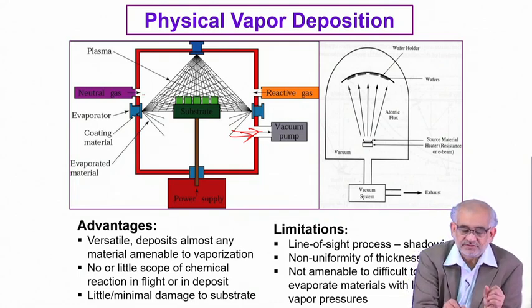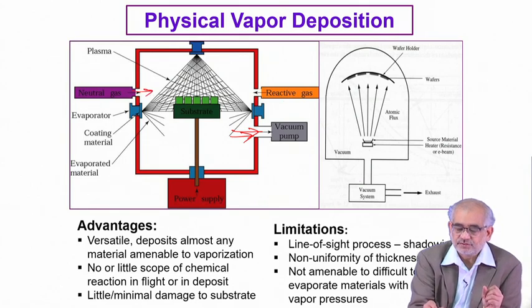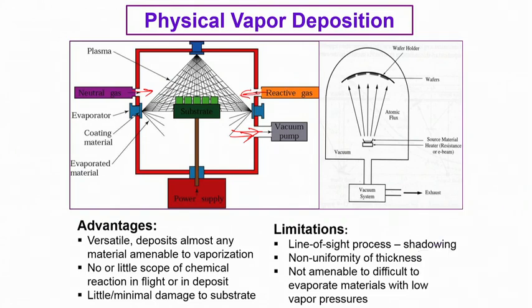You can backfill with neutral gas such as argon, or you can also feed in oxygen or nitrogen if you want certain reactions to take place, though this is not very regular. Feeding argon is fairly regular because once you evacuate and feed in argon, it remains neutral and creates a situation whereby undue oxidation is avoided. This is the substrate or stage on which you can place multiple components — 1, 2, 3, 4, 5 components.